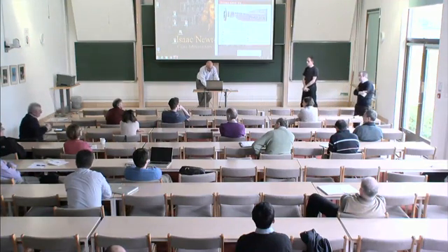Yes, there's still time. Again, when you spoke of the effect of shear, I think one possibility is that the first effect is changing the orientation of the smectic with respect to the surface. If you prepare your sample between crossed polarizers, it is black, because normally they tend to align perpendicular, homeotropic. By shearing the slide, you start to see textures because you're changing the orientation from perpendicular. Again, it is quite possible.